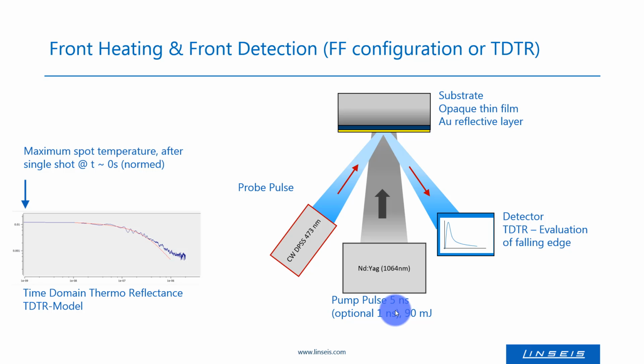What happens is that we locally heat a small spot on the front side of the sample with a short heating pulse and have a look at a subsequent temperature decrease of the spot. Here again, the signal is evaluated in a time domain, which, by the way, is the reason that this technique is called time domain thermoreflectance.